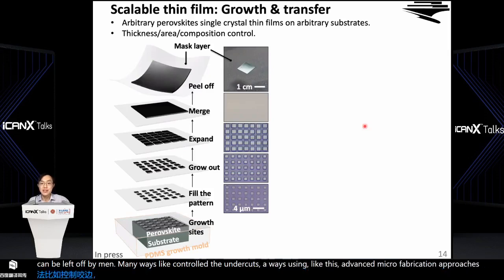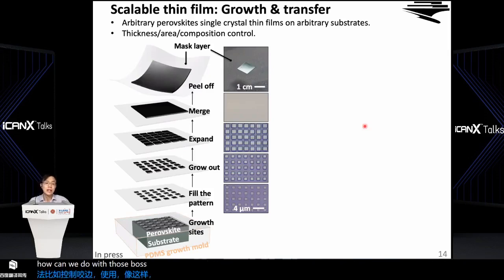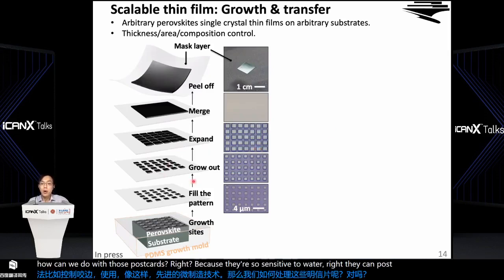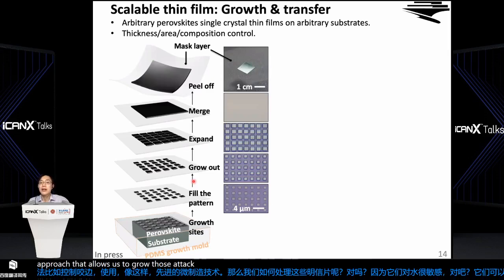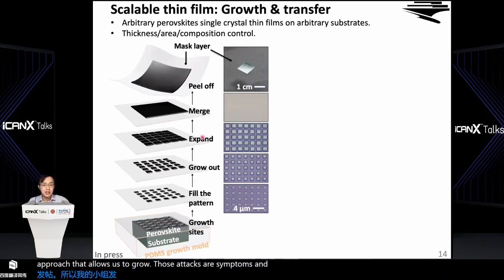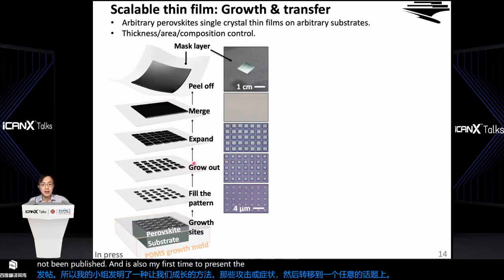Because they are so sensitive to water, they decompose. So my group invented an approach that allows us to grow those epitaxial thin films and then transfer them onto an arbitrary substrate. This result has not been published, and this is also my first time to present this in a public scenario like this. So what you're looking at here are a series of steps we use to grow and transfer